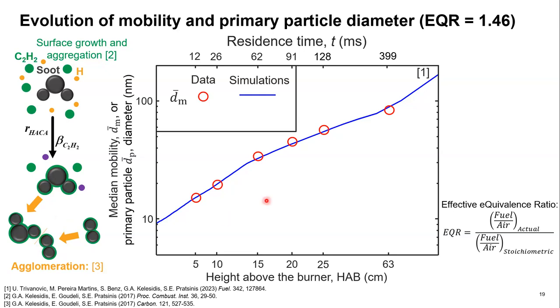So as we can see, these simulations were in excellent agreement with the experimental data that we obtained from our system. We also measured the median primary particle diameter, again from microscopy. And as we see experimentally, already at a height above the burner of 5 centimeters, we have approximately the same primary particle size as we do at the exit of the burner at 63 centimeters. So we've already obtained the final primary particle size as early as 5 centimeters above the burner.